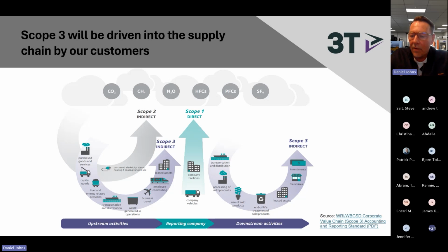Now, with those examples I showed before, it won't take long for companies to start to see that machining everything from billet is going to be a lot higher in embodied energy than going down an additive route. So we're getting ourselves in position. We're starting to do the measuring. We did a case study recently with a customer where the part they traditionally made through machining was 106 kilos of carbon, and through our value chain in 3T, it was 4 kilos. It was 102 kilos of carbon reduction.